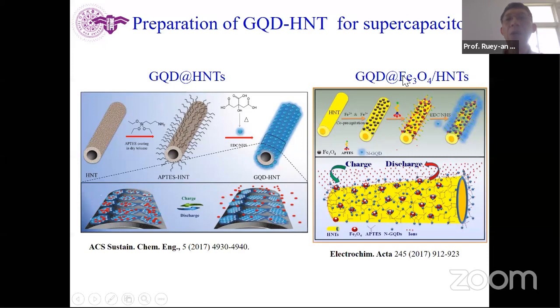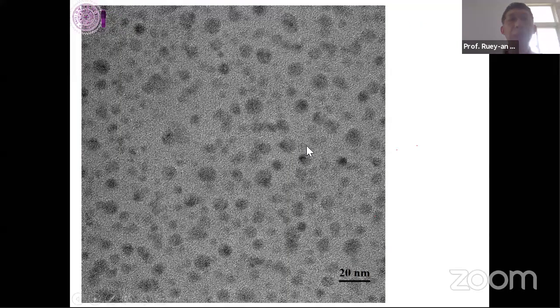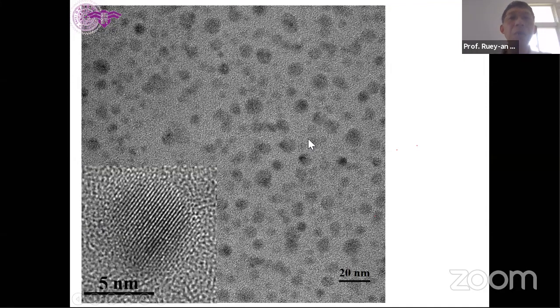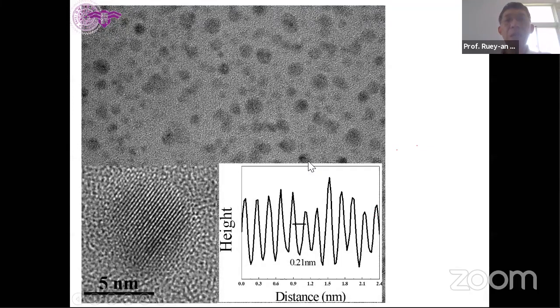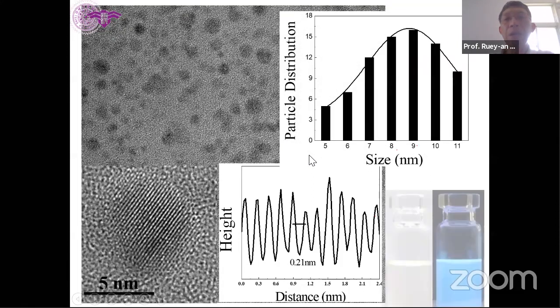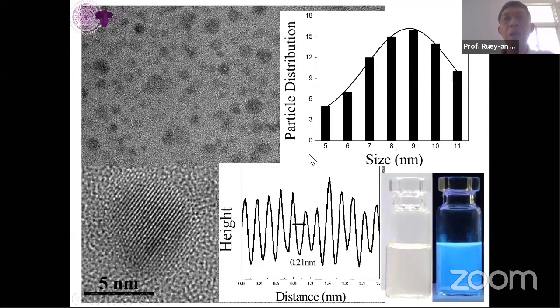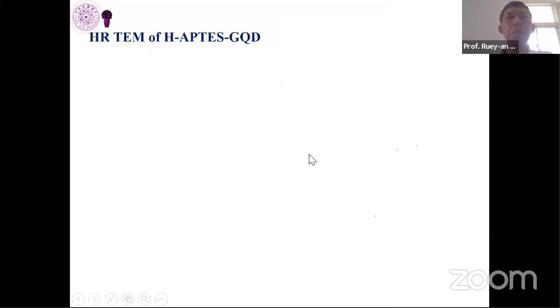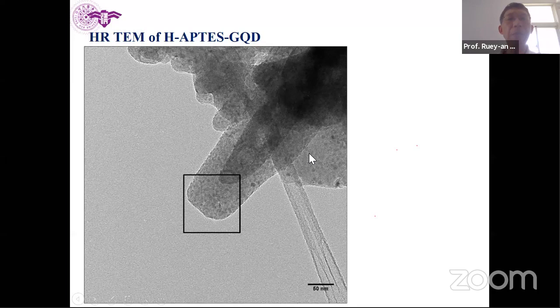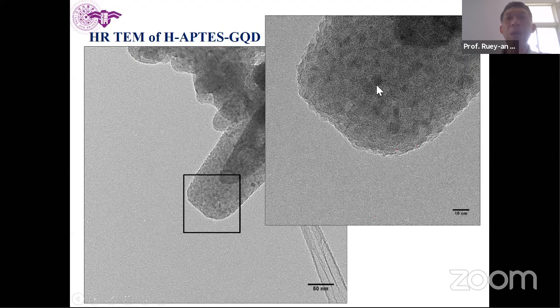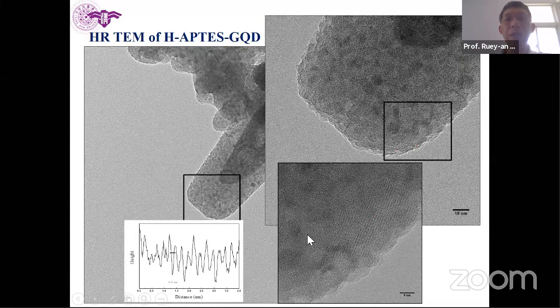If you would like to recover or enhance their properties, you can add some metal oxide, for example iron oxide or some other. So here is the case. Very briefly and quickly, we can still see a lot of graphene quantum dots, and the spacing is 0.21, very close to carbon. Their particle size is around 9 nanometers, very similar to the GQD we fabricated from passion fruits, and you can see they have quite good optical properties. And then when we put the GQDs on the tube surface, the outside is the tube. When we enlarge it, we can see some spots. This one is the graphene quantum dots here.